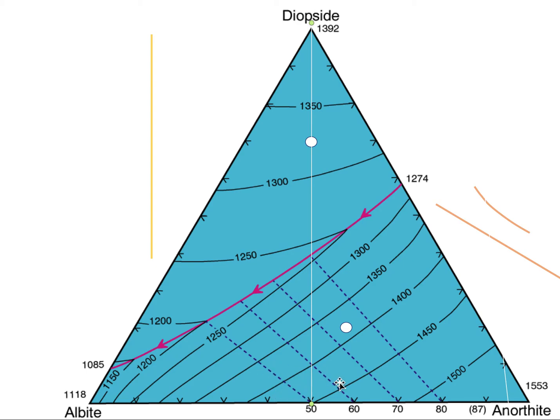So again, in a better diagram we might have many more of these dashed curves going from close to this edge here down to the albite corner. But in this case we can follow that dashed line up and so that would be our final liquid. Our final liquid would be here, rather rich in albite composition, and that final last little bit of liquid that will crystallize will occur at 1200 degrees. So at 1200 degrees the last little bit of liquid disappears. The plagioclase component as we go from this initial liquid here down to 1200 degrees has changed. Remember we said the initial composition was over here at AN80. As the liquid migrates down that curve, then the plagioclase becomes more and more enriched in the sodium rich or albite rich component. Until it reaches 50% anorthite and that's when the liquid is gone.